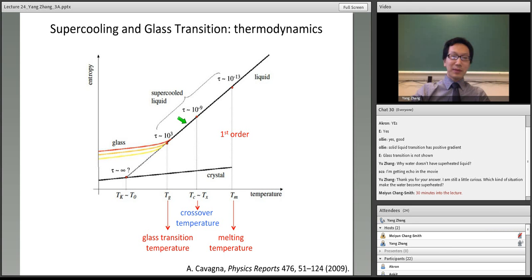Above this temperature, in this region, the dynamics of the material is still dominated by the self-motions. At a certain onset temperature, the so-called crossover temperature, the activated process begins, and many people describe this in different theories with different terms. Sometimes it's called cooperatively rearranging regions, or sometimes dynamic heterogeneity, or hopping. Below this temperature, those phenomena start to occur.